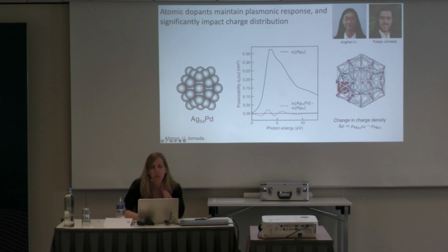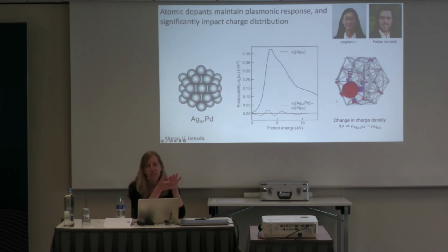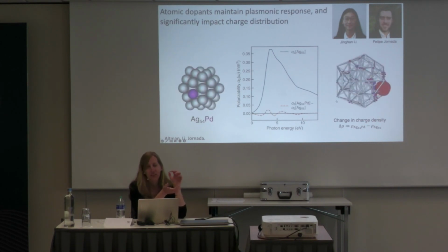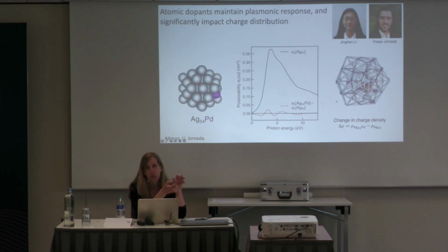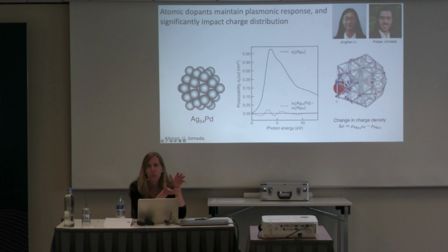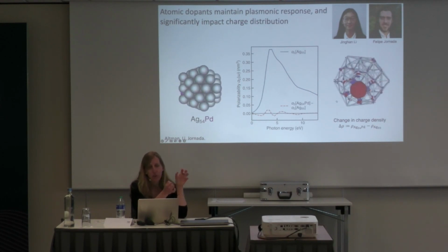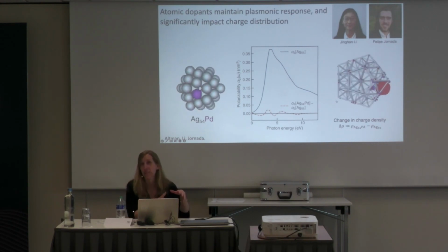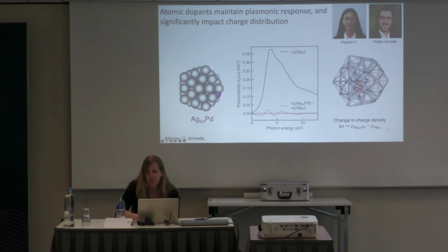But you do wind up getting this cool change in the charge density. So when he does these excited state calculations, you can start to see some of these theories that we had about hot carriers coming to fruition, where you don't change the plasmon resonance, but your charge distribution gets more centered over where you have these catalytic atoms when you are illuminating the silver nanoparticle. So you basically get hot carriers that get distributed over your catalytically active material.